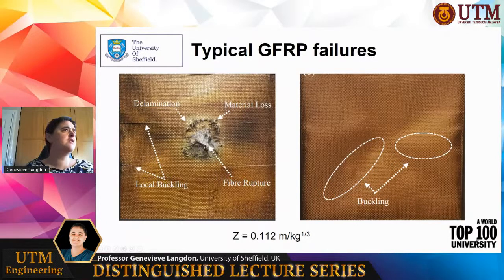So in the image on the left, you can see localized buckling. There's some delamination with a little bit of whitening from the kind of orangey color that you should see this panel to be. You've got fiber rupture and some material loss in the center due to the fact that this loading is extremely localized.